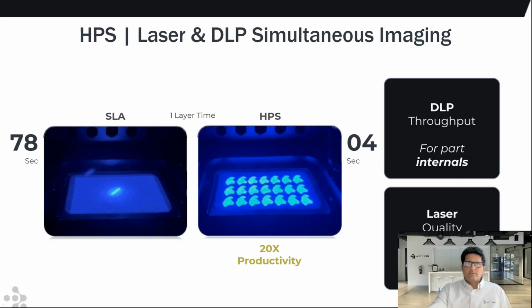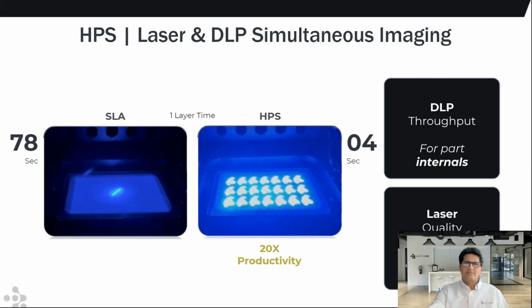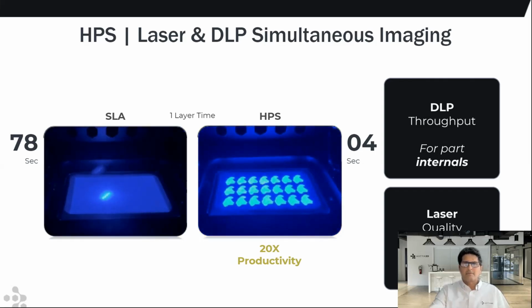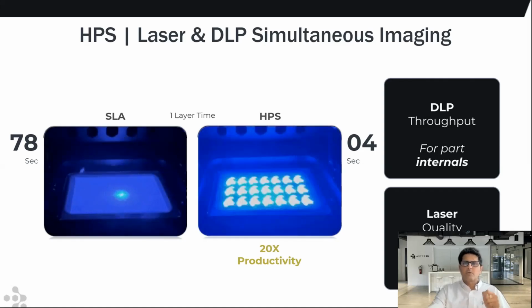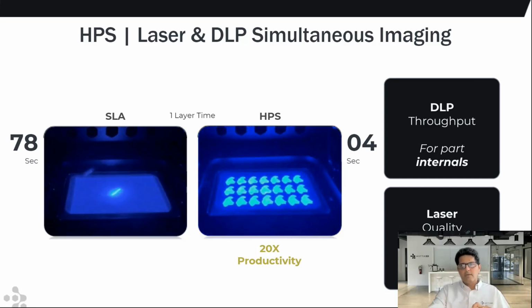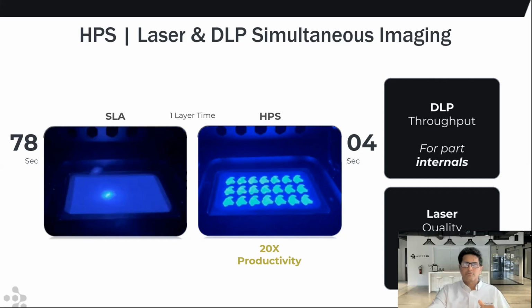Now, in this specific animation that you're seeing, if you look on the left-hand side, you will see that a single layer has been drawn by a laser, and it takes about 78 seconds for that laser to cure with conventional SLA, which just comes with a laser. Now, on the right-hand side, you see the laser and the DLP working simultaneously. And in our case, they work coaxially at the same time. It is not that a DLP follows the laser or the laser follows the DLP. They work simultaneously and coaxially to increase the throughput.